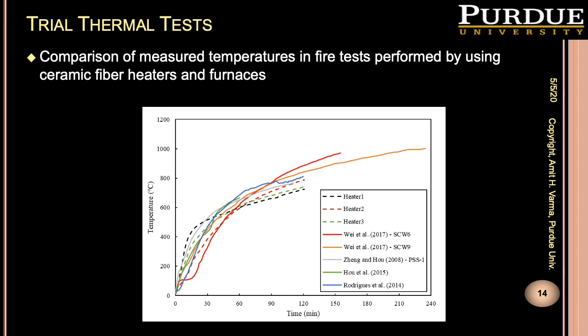Overall, this shows that the test method that we are going to use is quite comparable, and it's going to result in surface temperature time histories for the composite plate shear walls that is very comparable to that you would obtain from conducting a gas furnace test. Additional details of this, comparisons and discussions are provided in the report.